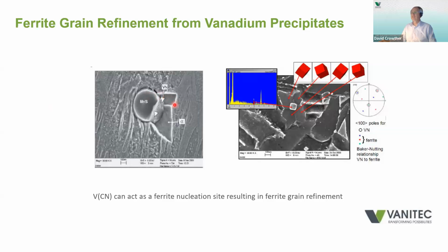On the left, we have a sort of composite precipitate with manganese sulfide and vanadium nitride, and a ferrite grain nucleating here. On the right, you can again see a vanadium nitride precipitate with 4 ferrite grains nucleating around it. And again, this shows that vanadium precipitates can refine the grain size, which is great for increasing both strength and toughness.